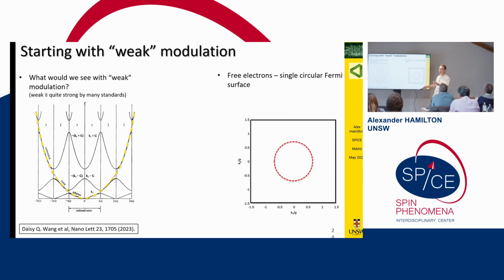And then when you put a weak modulation on it, you open up bands, and you know from teaching third-year solid-state physics that the size of the gap that you open up is proportional to the size of the modulation strength. It's the first harmonic. And then this gap is the second harmonic of that potential, and so on. And if you've got an isotropic system, then if I take a cut at a particular energy in the bands, I end up with an isotropic Fermi surface.